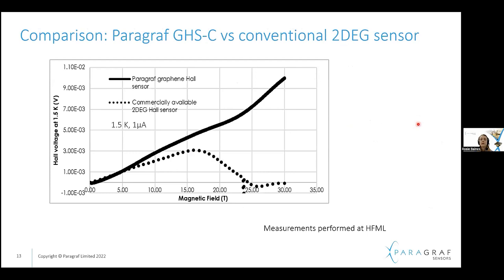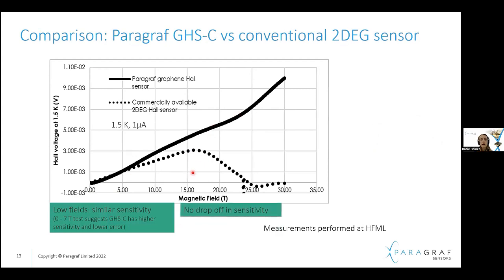So how does that compare to a conventional 2DEG sensor? Again, this is testing against a commercially available sensor, and we can see that at low fields, as it's swept along here, there's quite a similar response between the Paragraf graphene and the commercially available sensor. Whereas around 15-16 Tesla, we see a drop off in the 2DEG sensor, while the graphene still has that same linear response that we showed on the plot before.